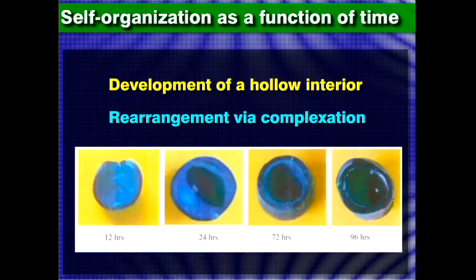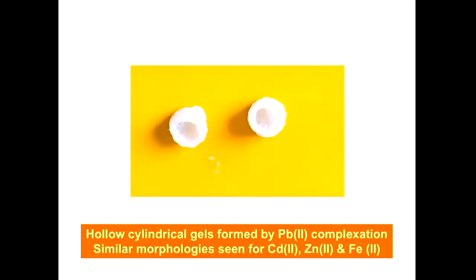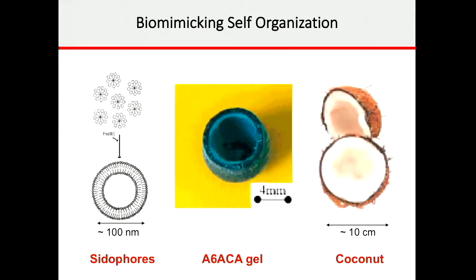The basic issue was, why should a cylinder turn into a sphere? Why should it change color? So we actually watched what was happening by taking cross sections. Not only did it turn into a soft sphere, but later on it turned into a coconut-like structure. And we discovered, after more detailed analysis, that it can happen also with other cylindrical gels formed with other transition metals like lead or cadmium or zinc. In fact, siderophores, for example, did this self-organization at 100 nanometers. The coconut did it at 10 centimeters, but our gel was intermediate, macroscopic self-organization, so to say.